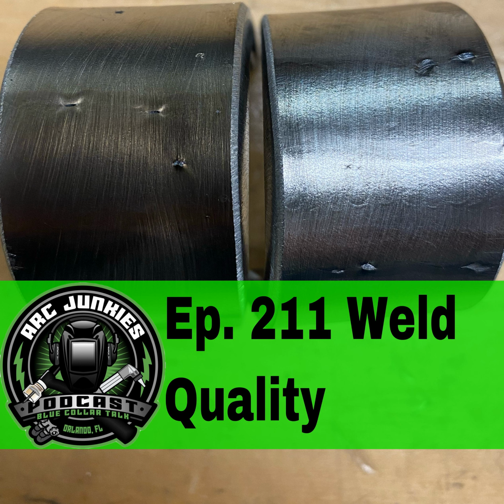Now, overlap is the protrusion of weld metal beyond the toe of the weld or the weld root. I explain this to people like a beer belly, right? Your belly Dunlopped over your belt. What this is, you traveled too slow with your weld metal. You created a lot of weld metal, and it's not properly fusing into the base metal, and it's creating a little lip or a little belly at the toe of the weld.